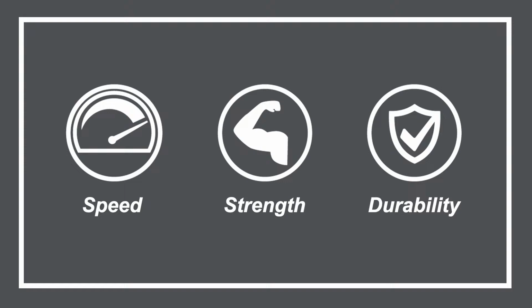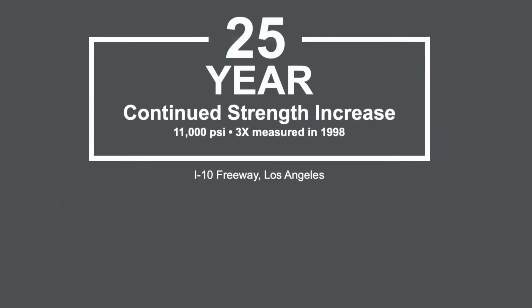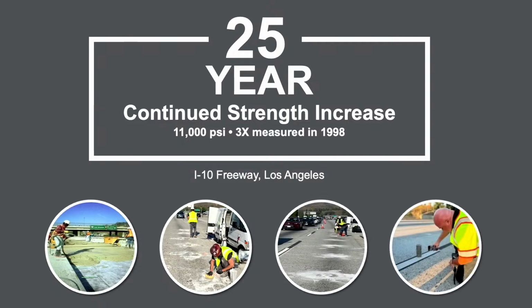These products are fast. Many of our Rapid Set cement products gain structural strength in just 1 hour. In addition to being extremely low shrinkage, they also have superior resistance to sulfate attack and long life durability. Speaking of durability, back in 1998, Rapid Set cement concrete was used to replace 2 lane miles on the I-10 freeway in Los Angeles. Fast forward 25 years later, and Caltrans allowed us to come out and sample that in-place concrete. And what we found is that concrete that was in the I-10 freeway for 25 years had a compressive strength of over 11,000 psi and a measured flexural strength of almost 3 times what it was at opening back in 1998.